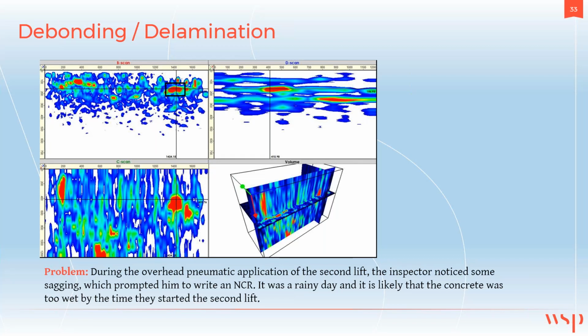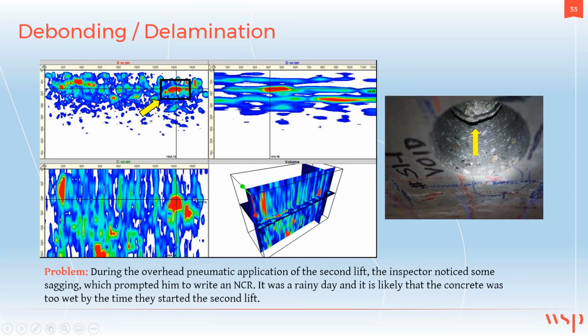But we were looking for potential debonding in the crown, and this strong reflection here seems like a good candidate for that. We took a core exactly here, and as you see, we found some major debonding.